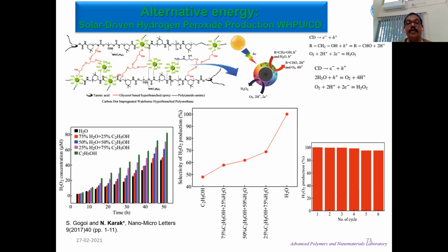We have also spent a little effort on generation of alternative energy, though due to facility limitations we are unable to go into details. However, we have seen that one of our polymeric nanocomposites with carbon dot can be efficiently used to generate hydrogen peroxide from aqueous ethanol. It is possible using water and ethanol separately, but with water the amount is more while selectivity is less, whereas with only ethanol, the amount is less though selectivity is high. So a mixture of 25-75% was found best for production of hydrogen peroxide by photocatalytic effect.